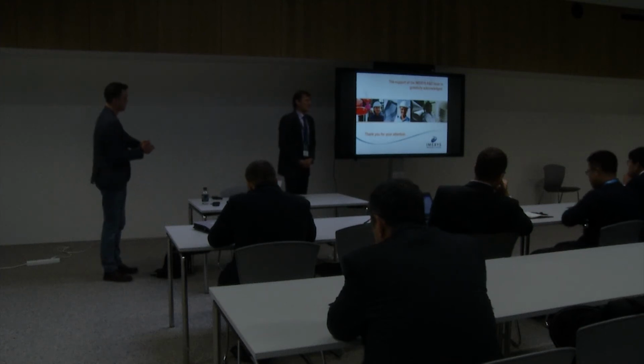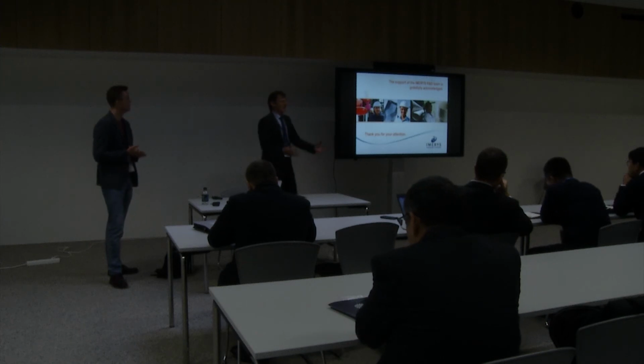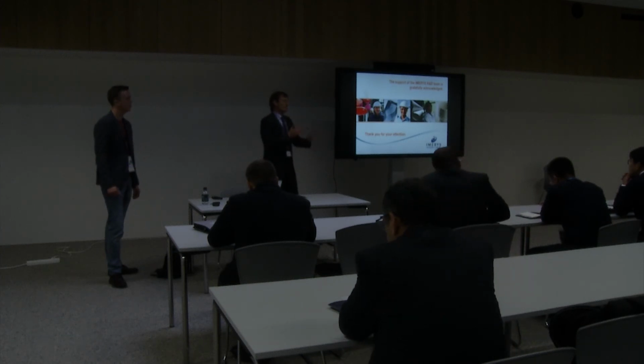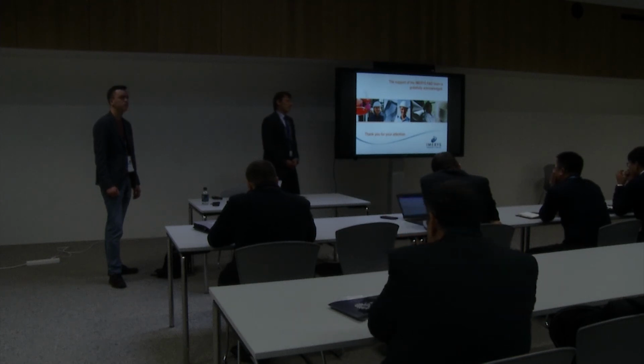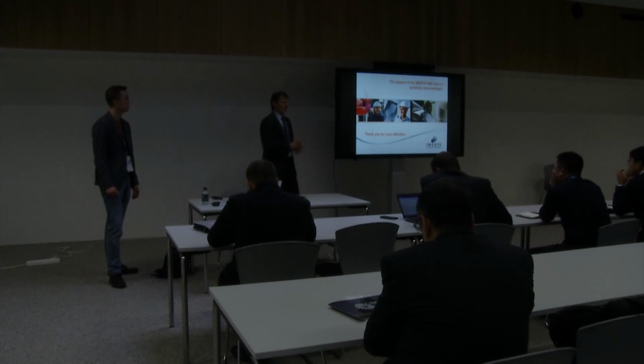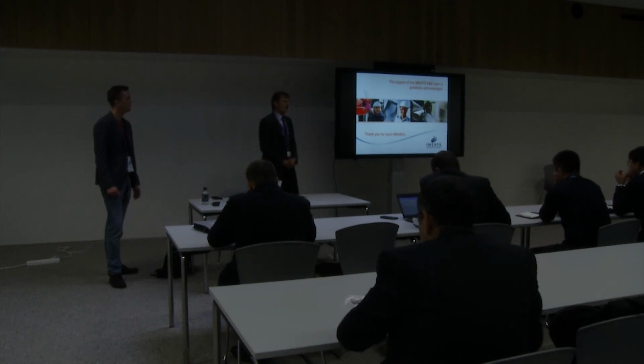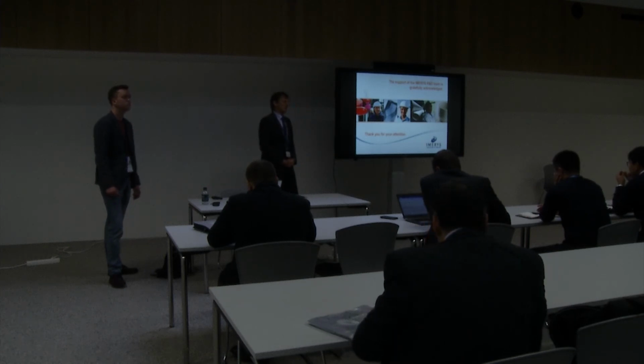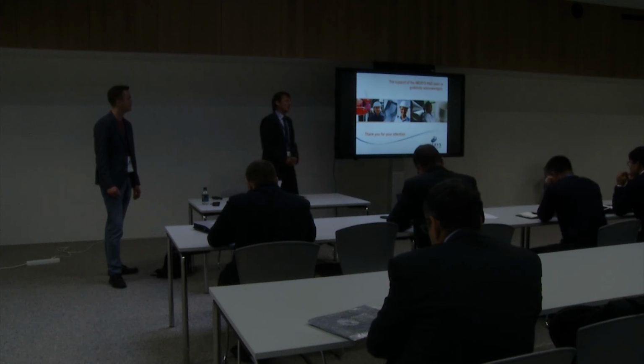Yeah, the surface, of course, can be different. If you look at a standard natural graphite anode material, most of them work with an amorphous coating that helps to adjust the compatibility with the electrolyte and controls many different aspects and parameters in the cell. A conductive graphite for sure works with other ways of optimizing the surface. So it is not coated with an amorphous carbon, otherwise you would lose the conductivity.